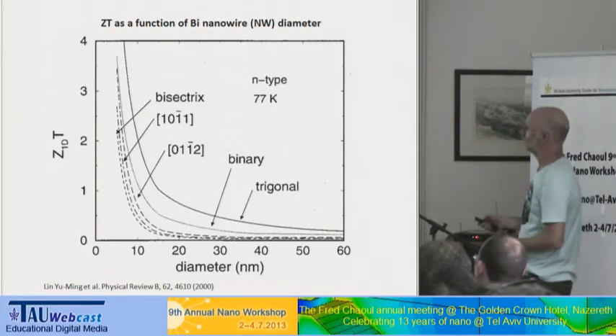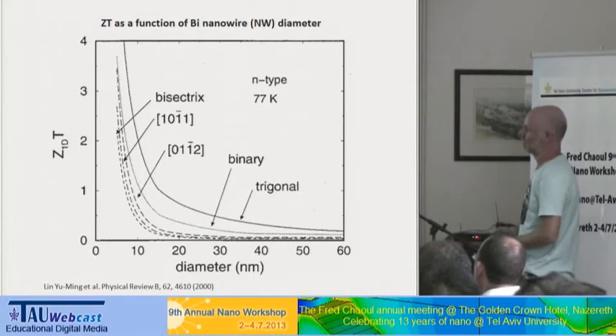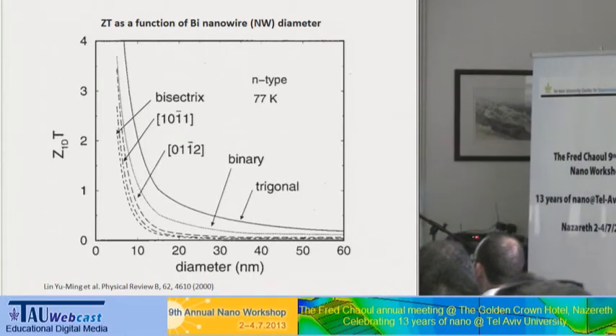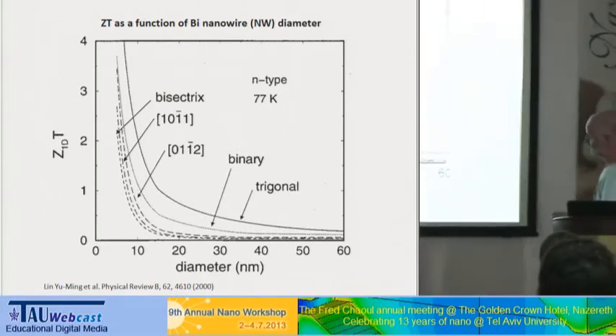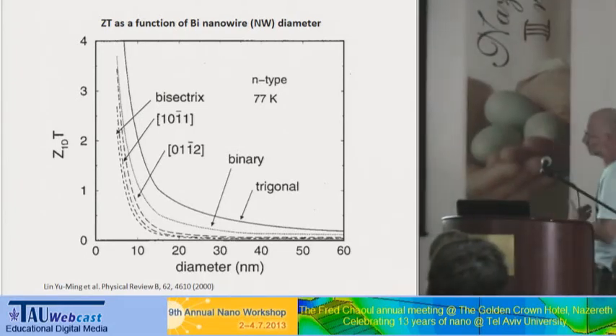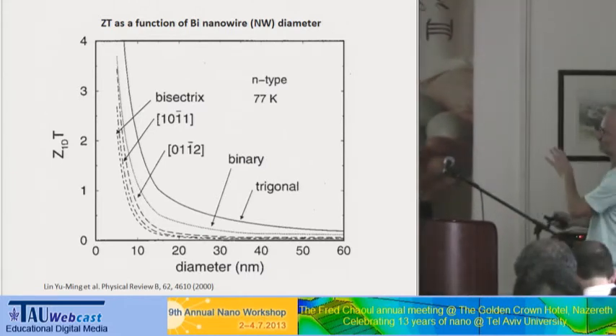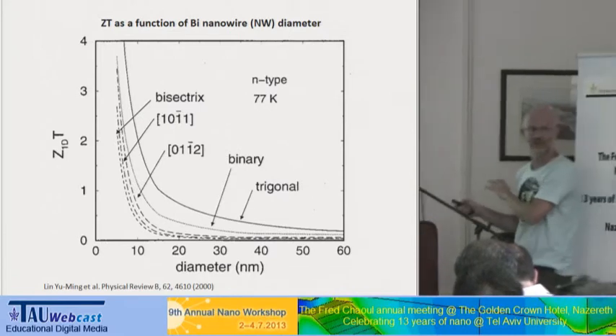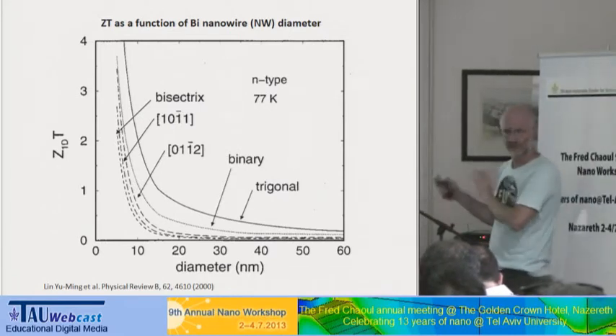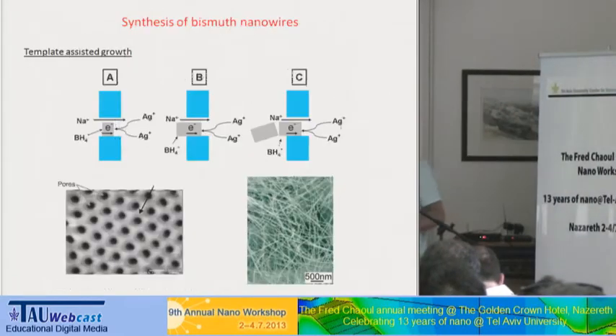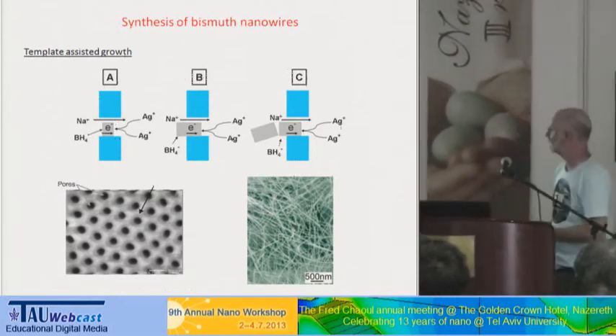And this was calculated at 77K because the electronic properties of bismuth are really complex, very temperature dependent, and they become much less dependent once we cross below 77K. So this is why they made a prediction at 77K, and all the results I'm going to show you today are at 77K, not at room temperature.